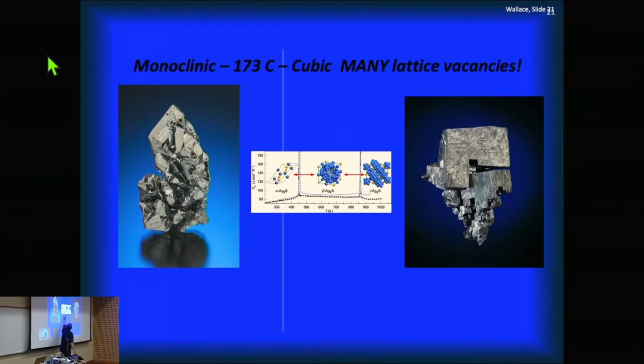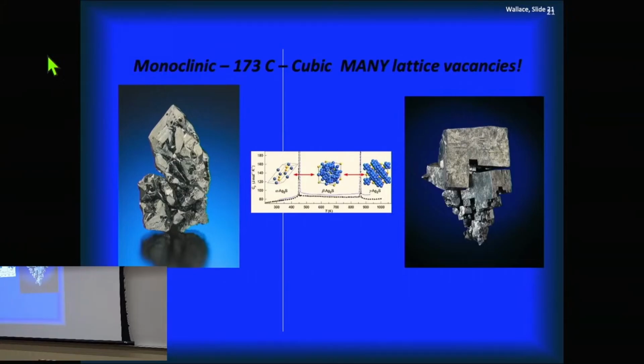anyway, what we see is that we suddenly go to this phase change, which makes it cubic. But where the silver is when we're in that cubic phase could be anywhere. We can actually go to very high temperatures, and then we go to a completely different body-centered cubic at high temperatures. But we don't have many of those specimens around from that high temperature. So we go from this monoclinic, kind of Roman sword looking thing to this cubic looking thing as we change temperature. All we did is expand that cage around that silver and allowed it to do its thing.